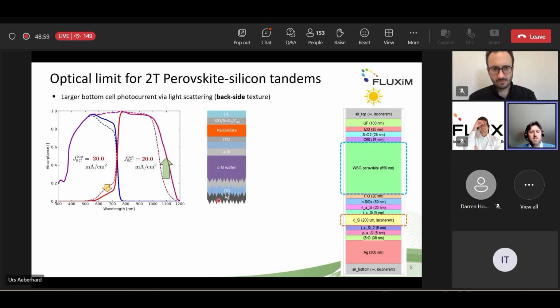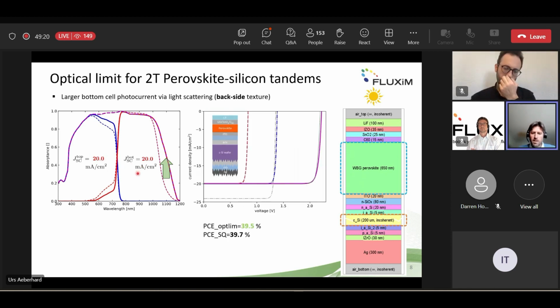If we do that, including this scattering texture, we see that indeed we can gain a lot of additional current here in the long wavelength region. There's also a small decrease, but this is again the situation where we find the optimum thickness for current matching. So now we are actually quite close to the Shockley-Queisser limit, well, how it is on this idealized absorption.